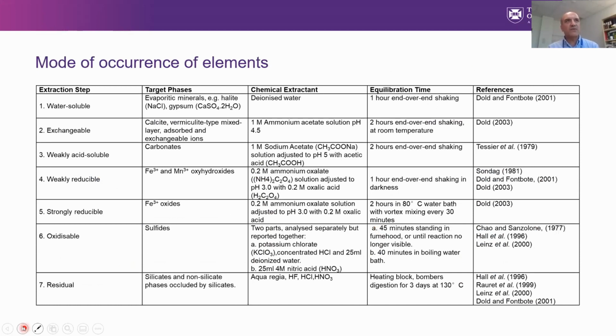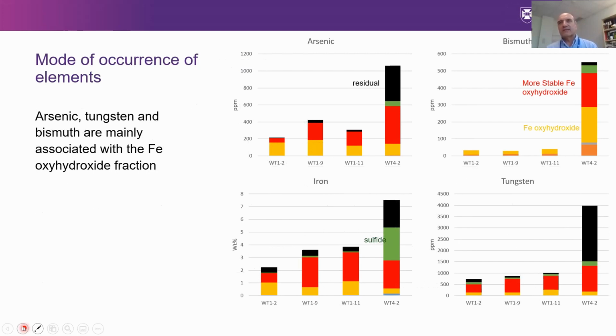So we want to understand whether it's water soluble, exchangeable, weakly acid soluble, weakly reducible, whether it is associated with iron oxide or sulfides or residual silicates. That's why Zheng Dong, the PhD student, has done a fantastic job going through this process of sequential extraction. And what we found is that tungsten is similar to that study in the US. Tungsten is associated with the iron oxide fraction, and even more the more stable fraction of iron oxide hydroxide, so things like goethite, for example, as opposed to ferrihydrite. So arsenic, tungsten, and bismuth are mainly associated with the iron oxide hydroxide fraction.